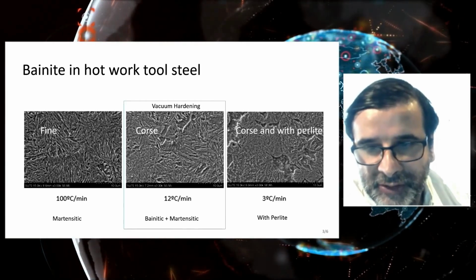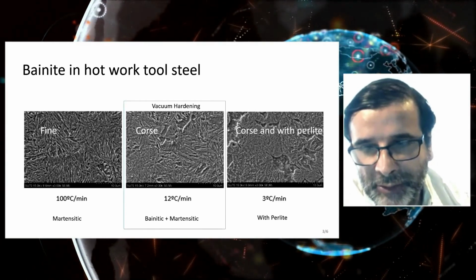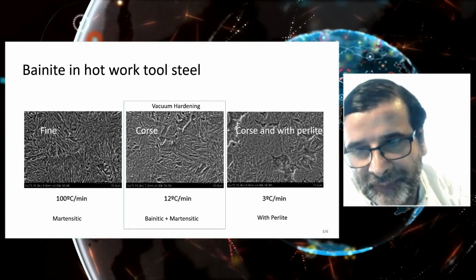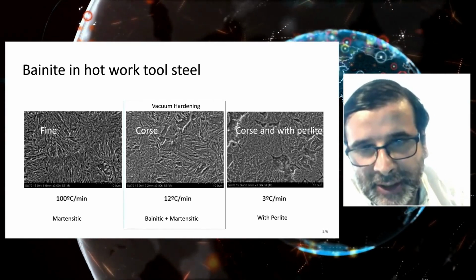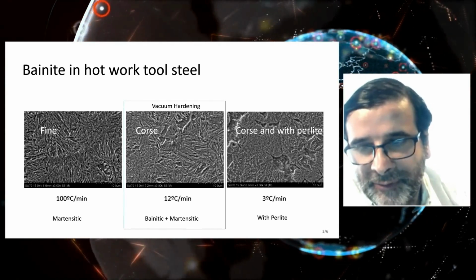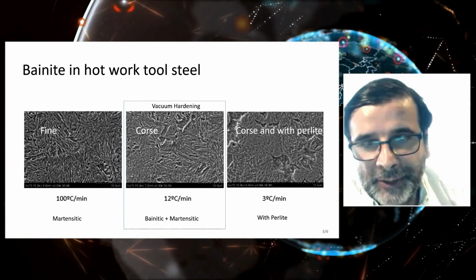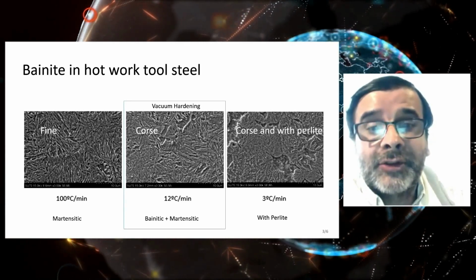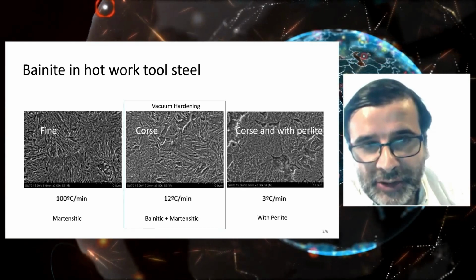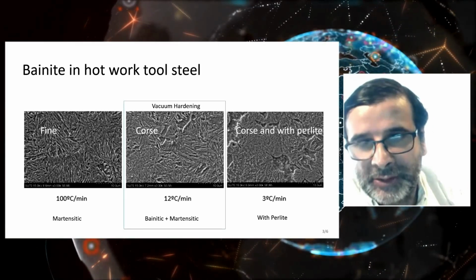Of course, the surface cools a little bit faster. The core will cool a little bit not so fast, and the typical average value for cooling speed of vacuum furnaces is around 12 Celsius degrees per minute. This will introduce a mixed structure. And if we speak about large dies, Ankit, do you have any definition of what is a large die for you in terms of tool? Is it by the dimension or by the kilograms?